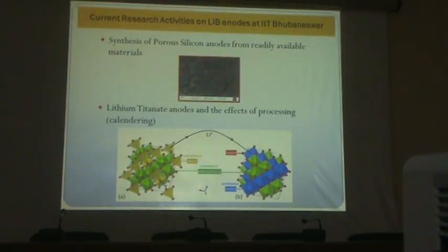The first student started working on the synthesis of porous silicon from readily available material. Why did we decide to do porous silicon? Because everybody agrees that silicon has around 300% volume expansion, so it's a very bad material to work with as an anode. It breaks and capacity fades within minutes. But they have seen that using porous silicon, battery life cycle can be increased.